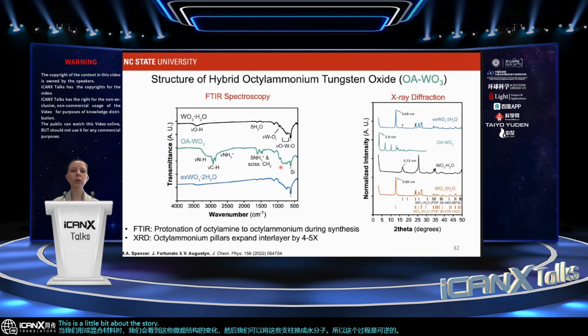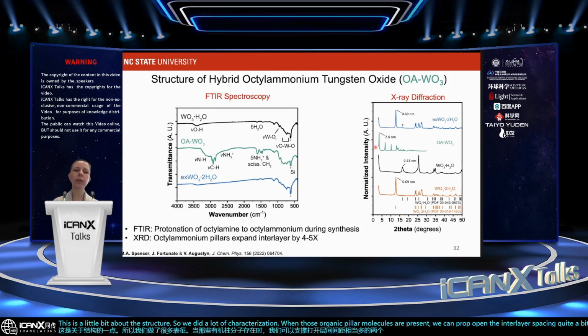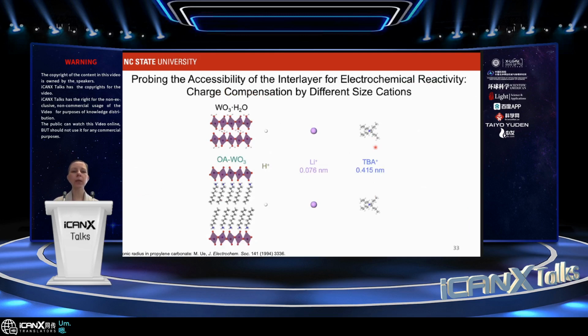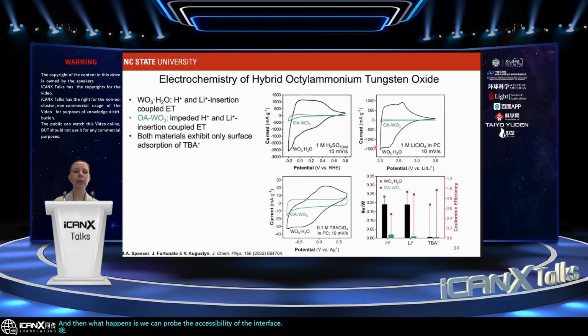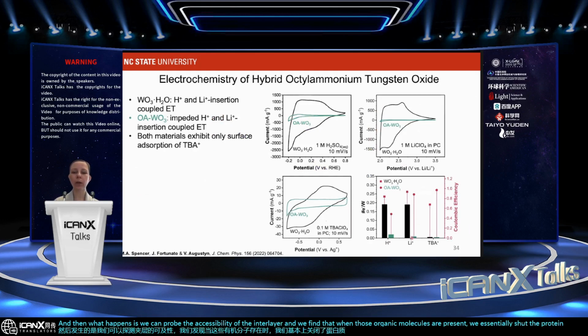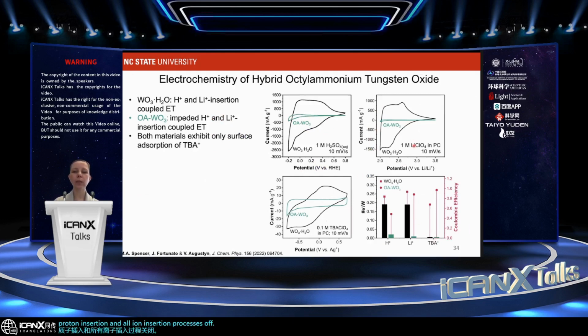This is a little bit about the structure. So we did a lot of characterization. When those organic pillar molecules are present, we can prop open the interlayer spacing quite a bit, up to 2.6 nanometers. So really open up the interlayer spacing in terms of the distance. And then what happens is we can probe the accessibility of the interlayer, and we find that when those organic molecules are present, we essentially shut the proton insertion and all ion insertion processes off. So whether it's protons, lithium ions, or tetrabutyl ammonium cations, we basically inhibit ion insertion into the material when those pillar molecules are present.